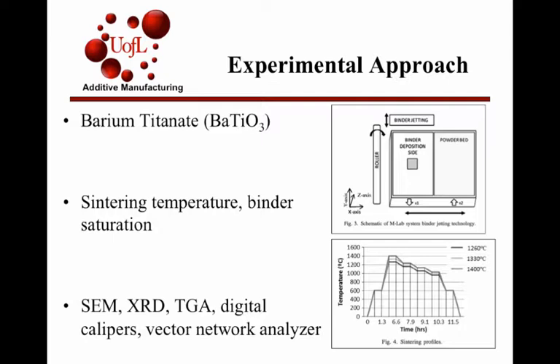So not only did they vary the sintering temperature, but a secondary test that they did was to vary the binder saturation, and that gave a preliminary test as far as which percentage was going to give the best results and the highest densities. And I'll go over that in a second.